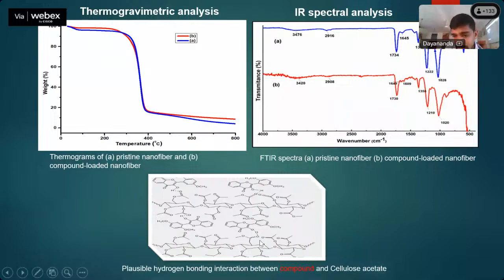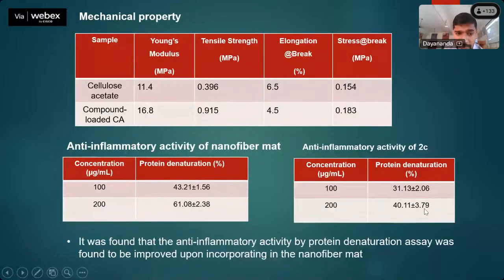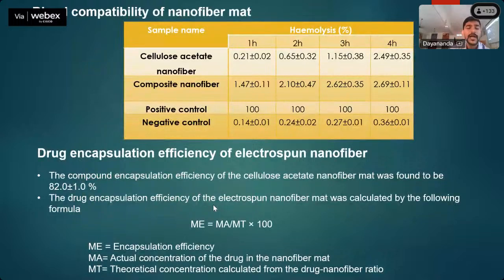This is more interesting: the anti-inflammatory activity of the compound at 200 microgram per ml was just 40% plus or minus 3%. But upon incorporating it into the nanofiber, the anti-inflammatory activity of the compound was enhanced or improved. That could be due to the nanofiber, which enhanced its anti-inflammatory activity.